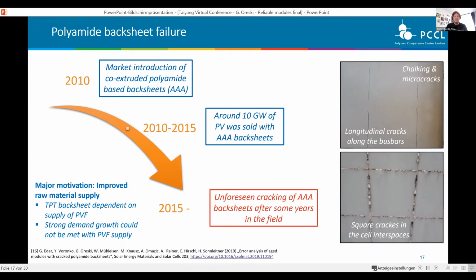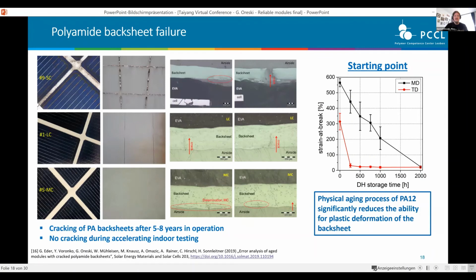And Isovoltaic decided going for polyamide. In the next years, around 10 gigawatt was sold. And unfortunately, after 5 to 8 years in the field, nearly all modules showed cracks, either these longitudinal cracks along the bus bars or square cracks in the cell interspaces. So we did a thorough investigation on the whole degradation mechanism, how these cracks are formed.